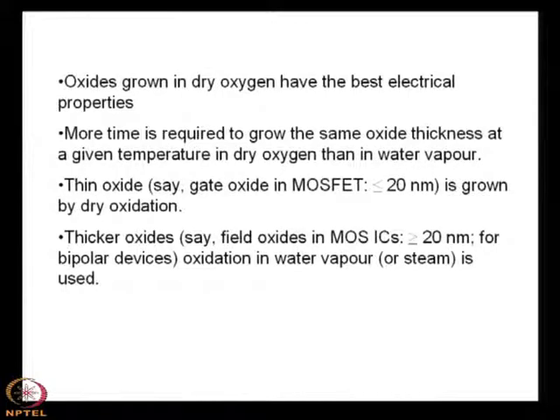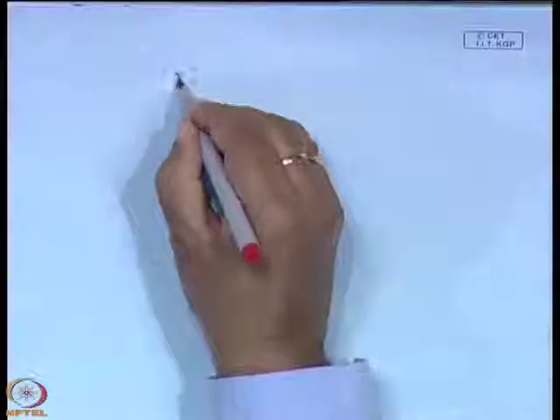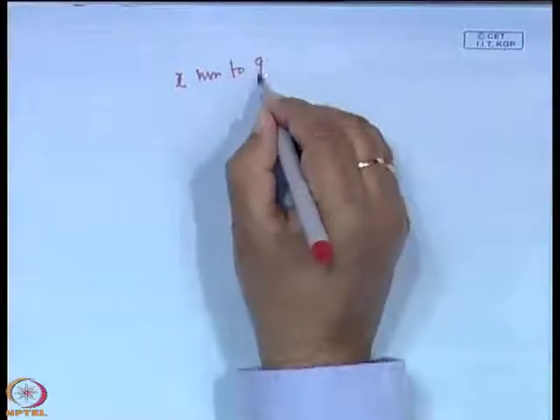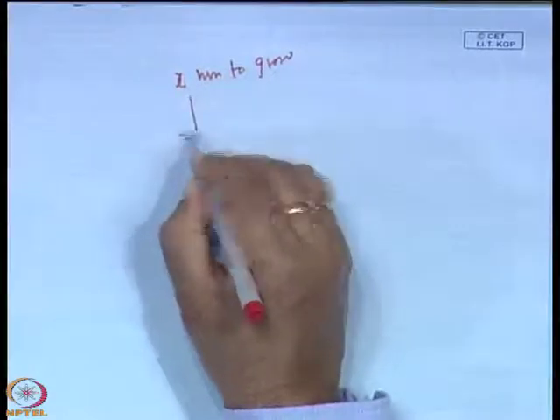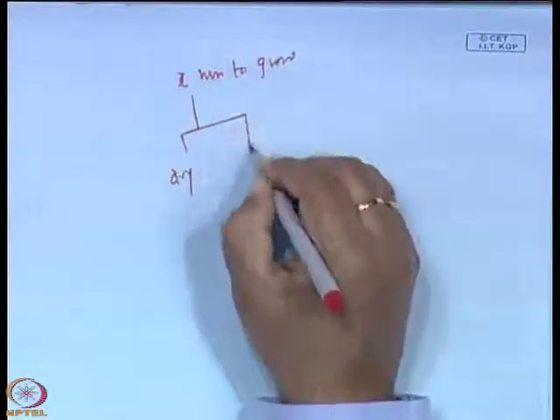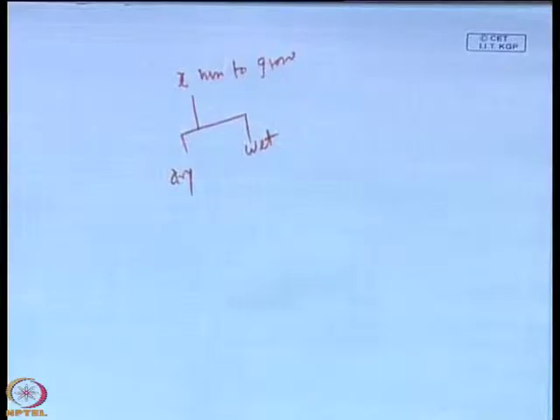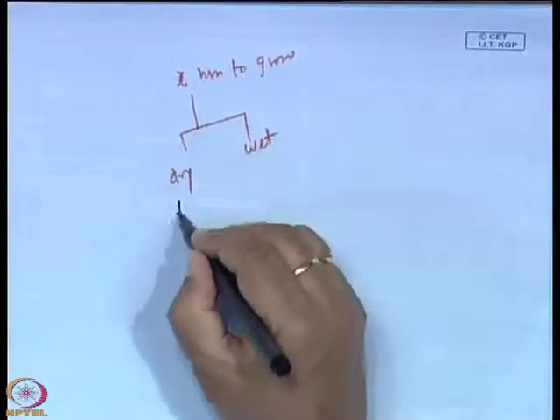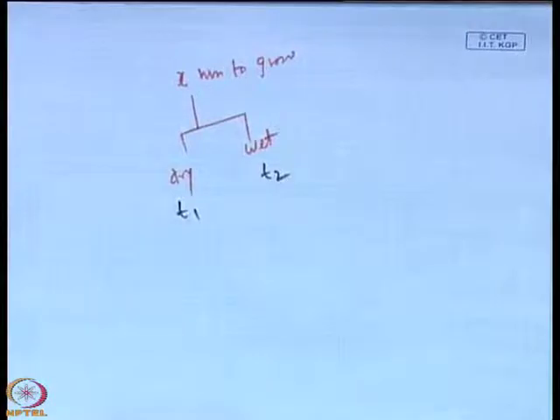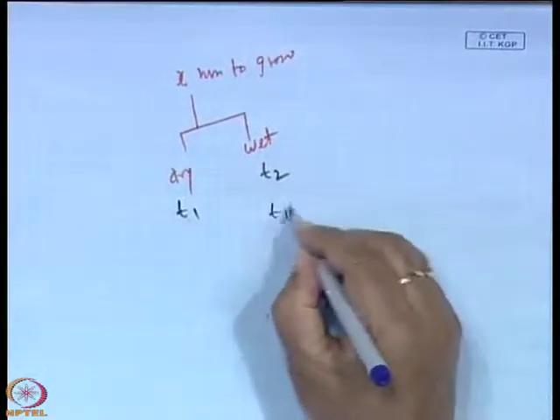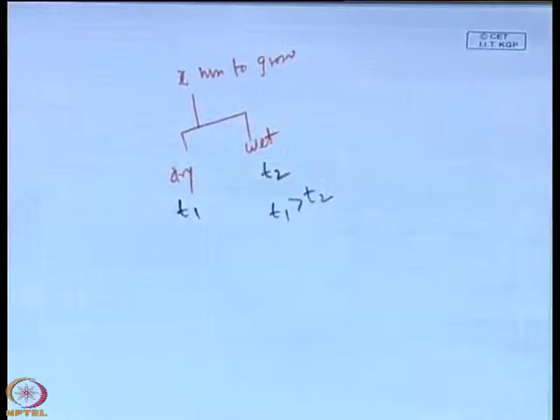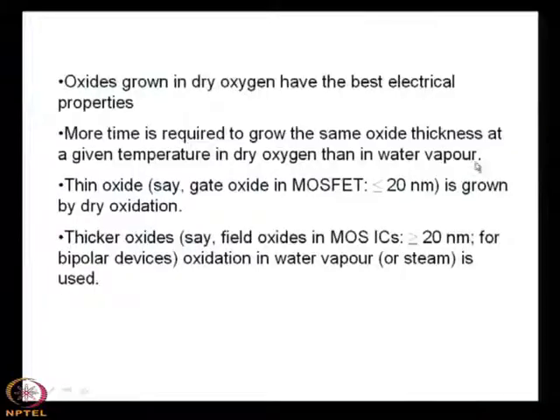then for x nanometer to grow, either by dry oxidation or by wet oxidation, the time required is say T1 and T2, and obviously T1 must be greater than T2. So, more time is required to grow the same oxide thickness at a given temperature in dry oxygen than in water vapor, and thin oxide is grown by dry oxidation.